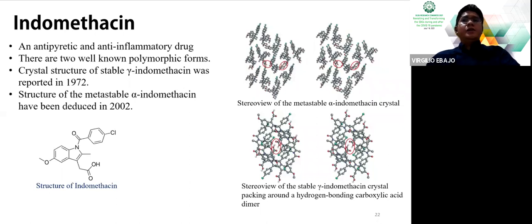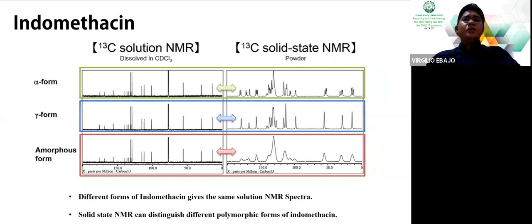The power of solid-state NMR in polymorph analysis can be seen in the analysis of the indomethacin polymorphs. Indomethacin is a commercially available antipyretic and anti-inflammatory drug, and there are two well-known polymorphs for indomethacin, the alpha and the gamma forms, which vary in their stability. The two polymorphic forms cannot be distinguished from one another using solution-state analysis, such as solution-state NMR. As you can see here, both the alpha and the gamma forms have very similar carbon-13 NMR spectra. You cannot tell one from the other by just looking at their carbon-13 NMR spectra.